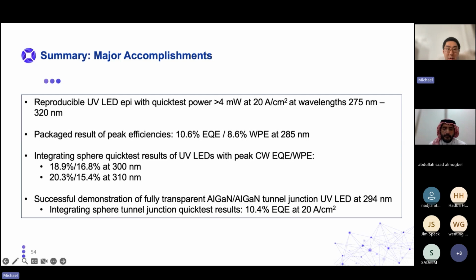And with the new results from 2025, we have integrating sphere quick test results of UVLEDs with indium contacts with peak EQE and wall plug of 18.9%, 16.8% at 300, and 20.3% and 15.4% at 310. And these will be improved on with future work. And we also successfully demonstrated fully transparent n-AlGaN to n-AlGaN tunnel junction UVLEDs at 294 nanometers with 10.4% EQE at 20 amps per centimeter squared.